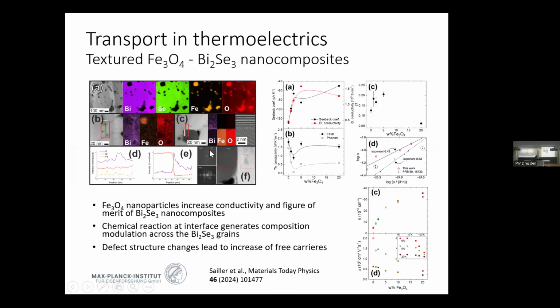So we did that. Following this idea of scattering centers, and because we knew bismuth selenide so well, we added the next complexity level, a secondary phase, more or less in the same direction that Ran was doing, but now adding complexity incrementally, not just all at once. In that case, we worked with a secondary phase to create scattering, but in this case it was an insulating material. We tried several ones. I showed the ones that we understood, which is the iron oxide. Why we use insulators is to avoid the question of what happens if we have a metal or something conducting in between. So we put something on purpose which is not conducting, although there is a slight conductivity for this iron oxide, and see what happens.